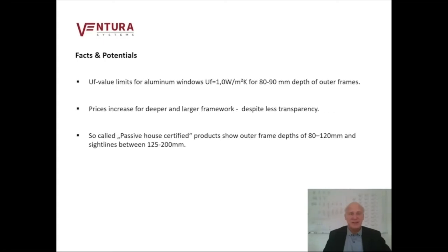Saying that UF value limits are given in the region of 1.0, and that requires depths of profiles of 80 to 90 millimeter minimum. It must be clear that we are facing price increases for deeper and larger framework, despite we have less transparency. So-called passive house certified products show outer frame depths of 80 to 120 millimeter and sightlines between 125 and 200 millimeter.